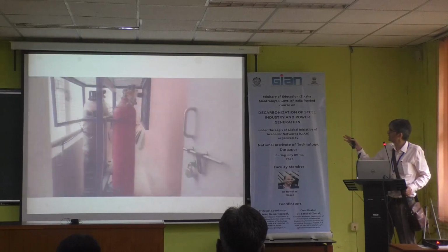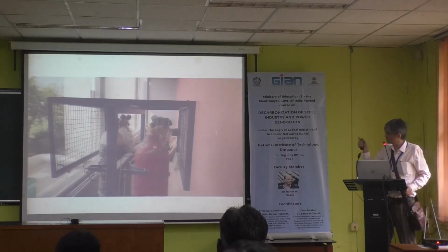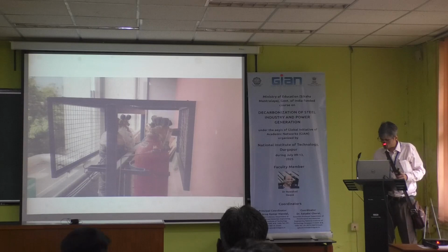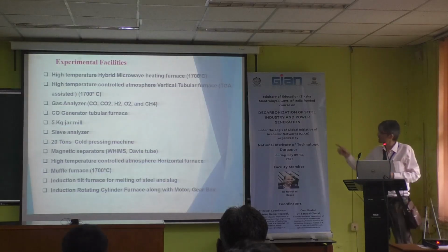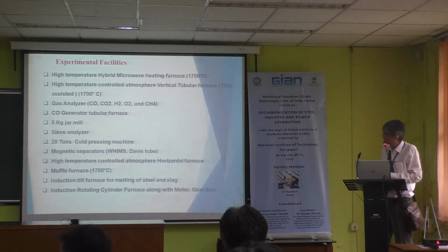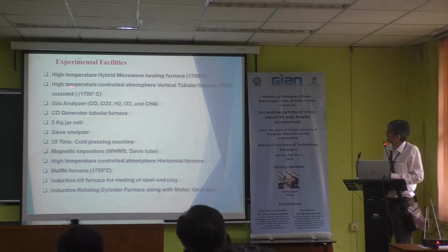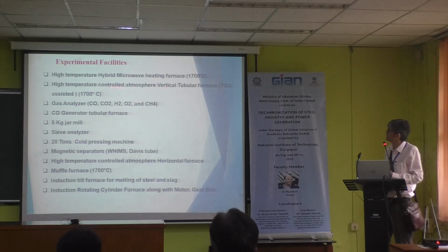These are the muffle furnaces. Then there is a microwave furnace. I will show these equipment in the video. The experimental facilities are as follows: a high temperature hybrid microwave furnace which can go to 1700 degrees centigrade; a high temperature controlled atmosphere vertical tubular furnace, which is a kind of TGA furnace and can also go to 1700 degrees centigrade; gas analyzers, a CO generator tubular furnace, a jar mill and sieve; 20-ton cold pressing machines for making pellets; and magnetic separators, a wet high intensity magnetic separator and a Davis tube.